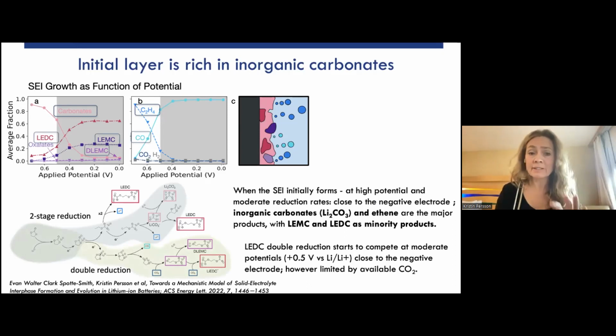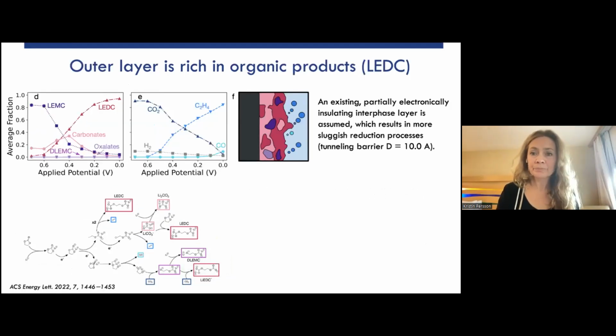But in this particular reaction, it's limited by available CO2. So now the first film that forms, if you believe these calculations and the different paths that we picked out and the competition between them, the majority species close to the electrode are inorganic carbonates with some gassing and a little bit of inclusion of organics.